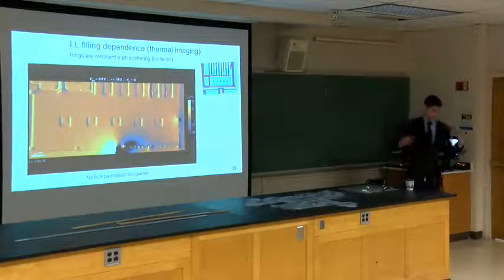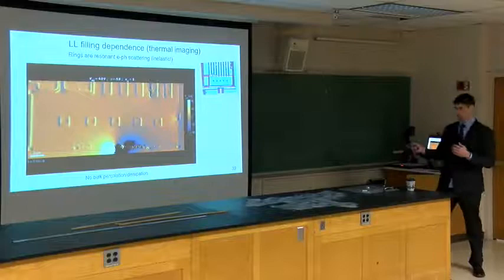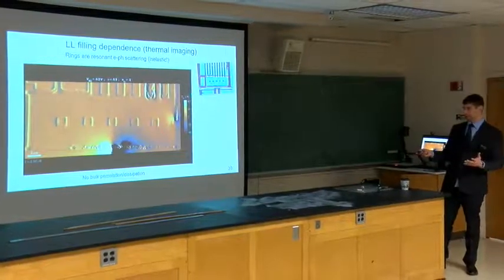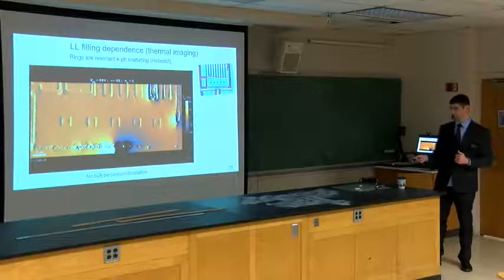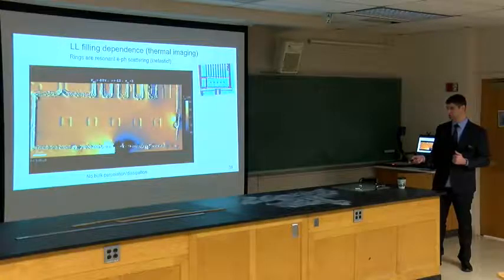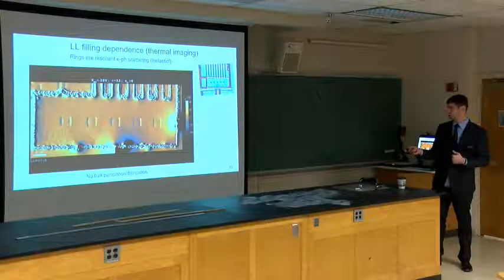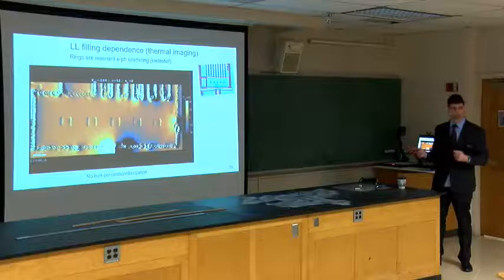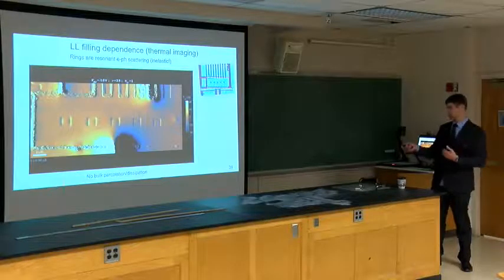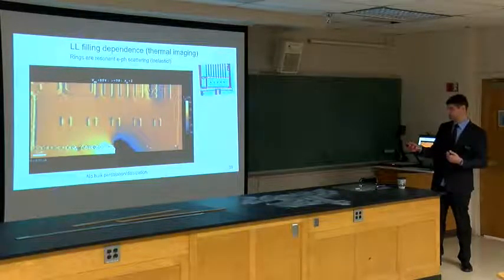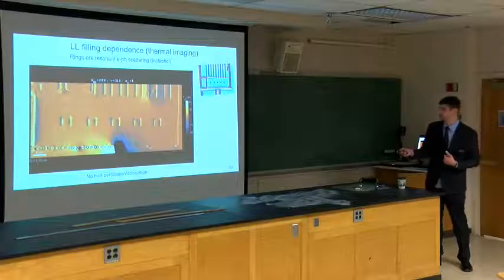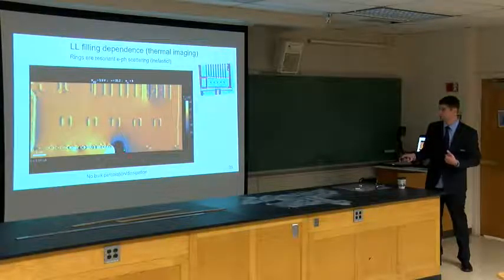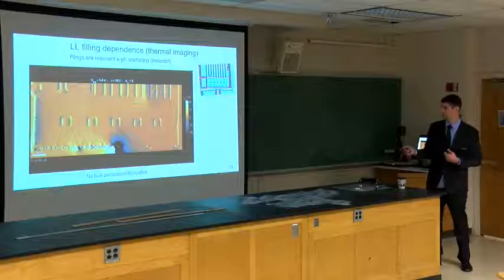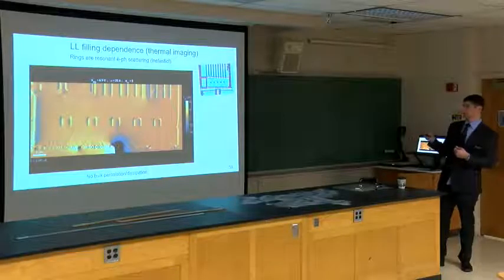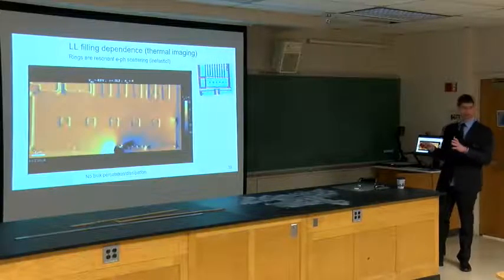Now, if we take that system and we apply 1 Tesla, so we're firmly in the quantum Hall regime, we pass current between this electrode here, which is, on the previous device that I showed, a small contact, so we're injecting some degree of hot electrons into the quantum Hall states. We're passing current from here to here, and in this case, we're not measuring any resistance.